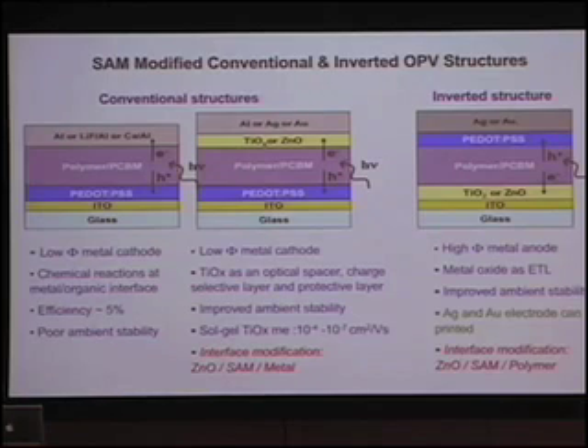When you shine light on it, electrons will be collected and go to this low work function electrode, and holes go to this conducting polymer as an anode here. You can get an efficiency around 5%, but because of the low work function metal you use for the cathode, you actually create a lot of problems for the environmental stability of your devices.